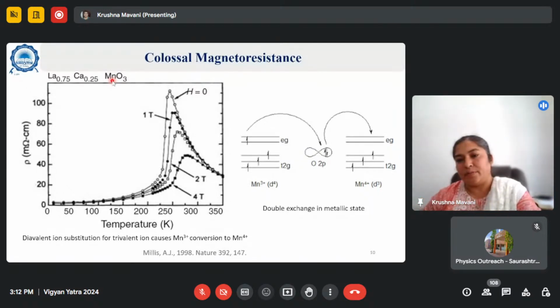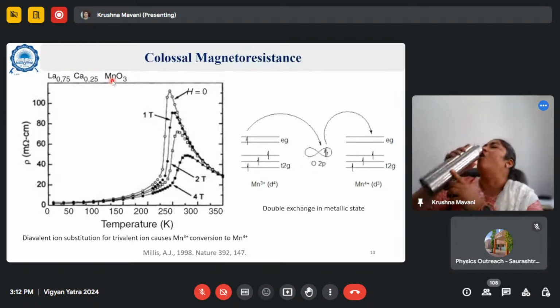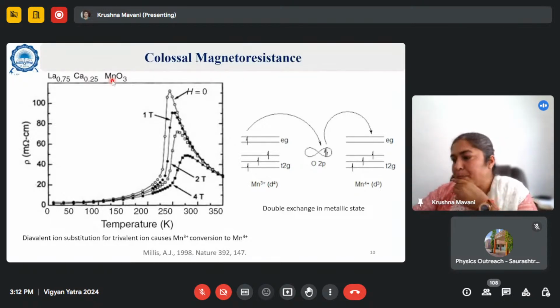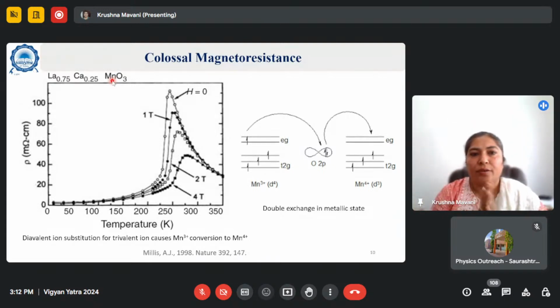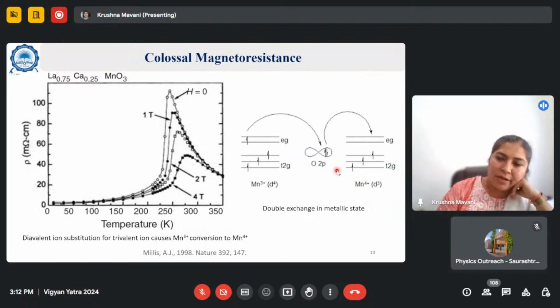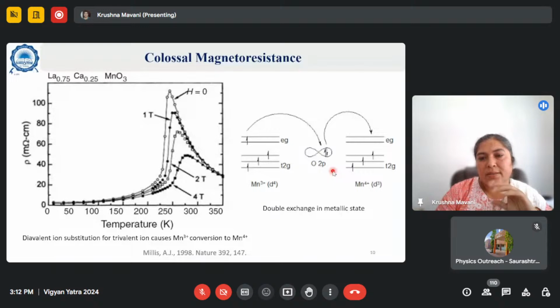And as you apply a magnetic field, what happens, I would like to explain here as a double exchange scenario. Initially your manganese was just 3 plus, 3 plus, but when they are like Mn-O-Mn chains with manganese trivalent and manganese tetravalent, the manganese tetravalent has a vacancy here for an electron. Now, oxygen 2p orbitals overlap with 3d orbitals of manganese. So this electron can have double exchange, first with the oxygen 2p orbital, and then again with Mn4 plus. So basically this Mn3 plus and 4 plus is a kind of dynamic state.